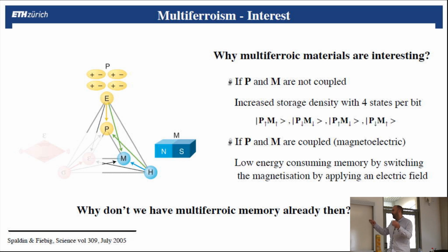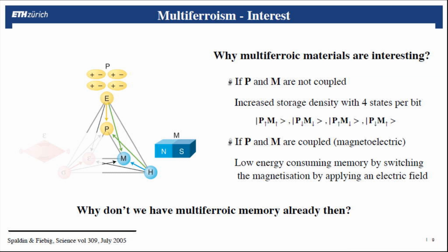Why are they interesting? For many reasons, but here are two possible applications. Imagine that in the same phase of your material, meaning at the same temperature, in the same conditions, you have a material that has polarization and magnetization. If polarization and magnetization are not coupled, meaning that you cannot influence the polarization by the magnetic field or the other way around, then you could have four states in your system. You could have spin up, polarization up, spin down, polarization down, or the other combinations. So that would result in a higher density storage device. If they are coupled, meaning that you can influence polarization by magnetic field or the other way around, then you could switch the magnetic moment of your system not by applying a magnetic field, which is very energetically costly, but by applying an electric field. And that's why these are interesting materials.